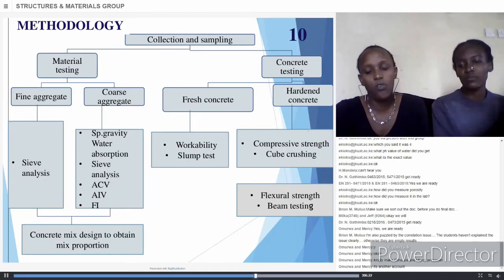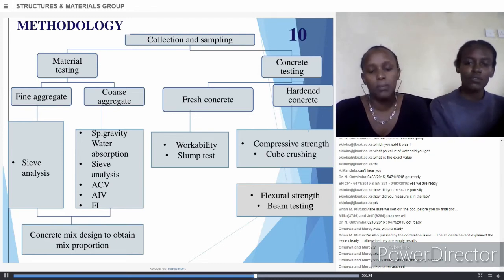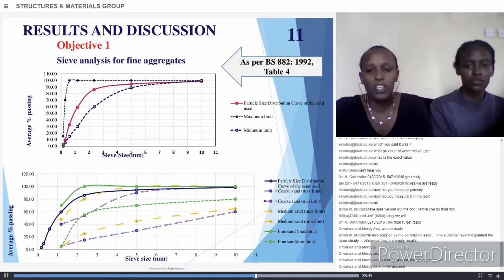Our methodology, from our objectives: we determined the properties of coarse aggregates. Then we determined the properties of both fresh and hardened concrete, and from the optimal mix, after the mixing, we determined the flexural strength by casting the beam. The sieve analysis of the sand was within the envelope, and it was good to produce quality concrete.